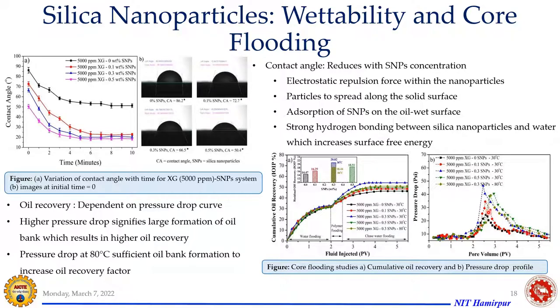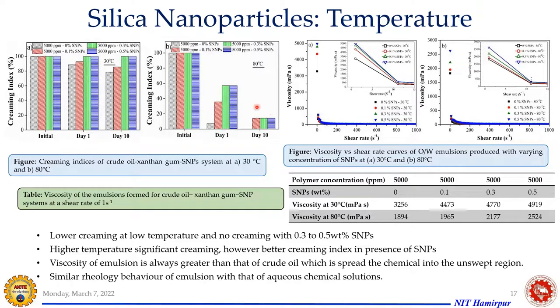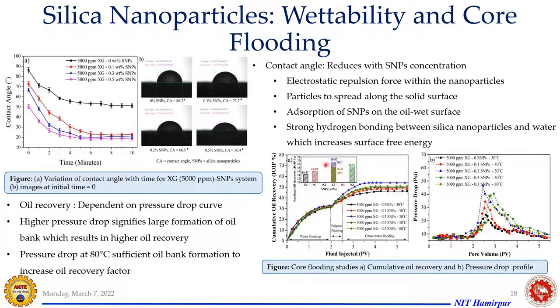So we have also identified this pore blockage by performing some characterization, like analyzing the FESEM image of the rock pores, through which we have also seen that there is a blockage. Okay. And one of the important things is the effect of temperature. So you can see here, even though at high temperature we are having this much creaming, still we could produce an oil recovery of around 18.5.